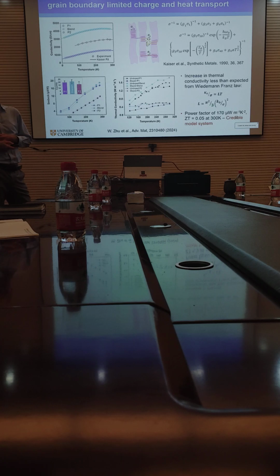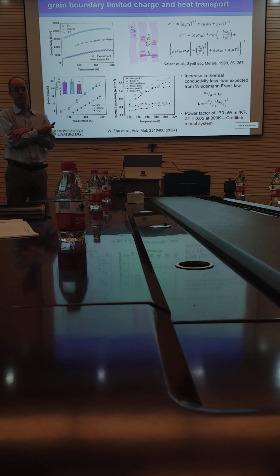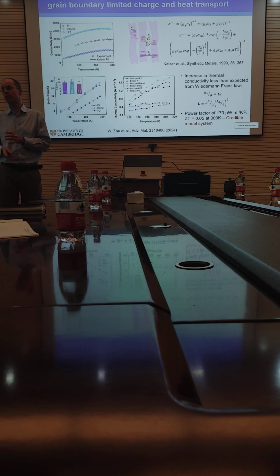So if this law was valid, we can plug in our electrical conductivity sigma, 5,000 Siemens per centimeter, at the optimum point. Then our electronic contribution to the thermal conductivity should be 3 watts per meter Kelvin. So the total thermal conductivity should be somewhere up here. So the fact that we only see a thermal conductivity of around 1.4, 1.6 means that this Wiedemann-Franz law is not valid in this system. That's good from a thermoelectric perspective, because we don't want the thermal conductivity to be increased much.